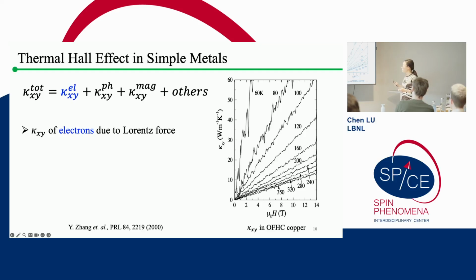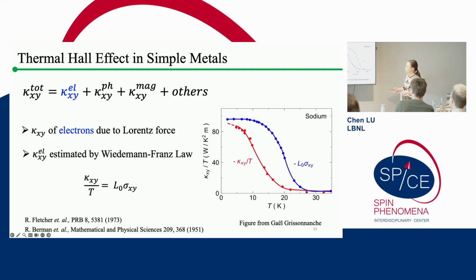And one thing we know for metals is something called the Wiedemann-Franz law. The Wiedemann-Franz law tells us that we can always use the electrical Hall conductivity to estimate how much the electrons can contribute to the thermal Hall effect. So basically, this formula tells us the thermal Hall conductivity divided by the electrical Hall conductivity should be equal to some constant. The figure on the right-hand side, exactly the blue curve, is the electrical Hall conductivity estimation coming from sodium, which is another elemental type of metal. And then the red curve is the actual thermal Hall effect that has been measured in this material.